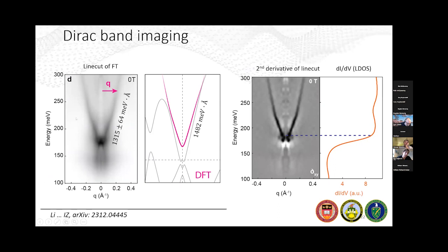So this is the STM data here on the left. You can see this Dirac dispersion actually occurs at positive energies, which is something that would not be accessible by ARPES, but we compare this to theory, and this is what theoretical calculation tells us. If you compare the dispersion that we get and the dispersion that you would get from DFT calculations, it matches very well.